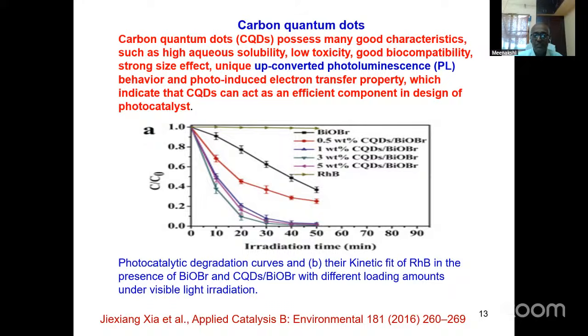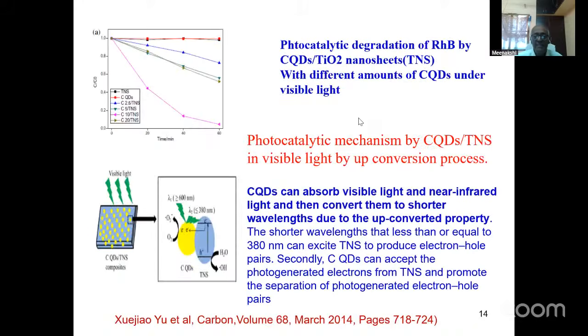Here the upconversion is not there, but 3% CQD bismuth oxybromide is found to be efficient in degrading the dye rhodamine B. And here you can see titanium dioxide nanosheets with the carbon quantum dots, and the 10% carbon quantum dot titanium dioxide nanosheet is found to be most efficient in degrading this rhodamine B.